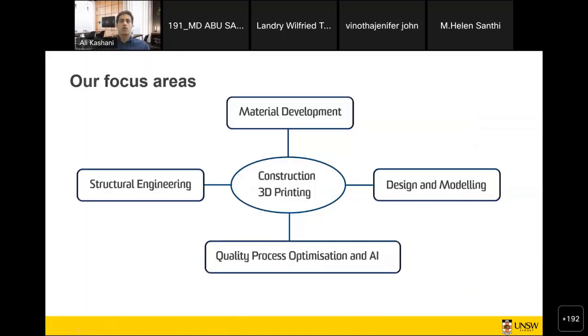Okay, so what we are doing in terms of research in construction 3D printing: we've been developing materials, as I discussed, for 3D printing for quite a while. And this is not just for the lab environment. As I mentioned, when you go to the field, on-site printing conditions are very different. You get very high drying shrinkage, and the hydration of the material can be challenging. You may develop cracking. Those are things that you don't see in the lab environment, and it's very new to us. We've been seeing it during our field trials, and we've been working on it.